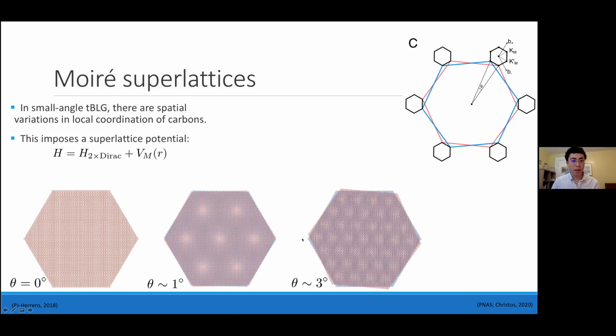In the third one you can kind of see at the corners here the two hexagonal sheets discernibly rotated relative to one another. And we see, if we were to do this in some sort of movie, that these bright spots shift as a function of time continuously. And what do the bright spots correspond to? Well, they correspond to the coincidence of certain carbon atoms in the top and bottom layers, because when carbon atoms are coincident, then so too are the spaces in between them, in the middle of their hexagonal cores.